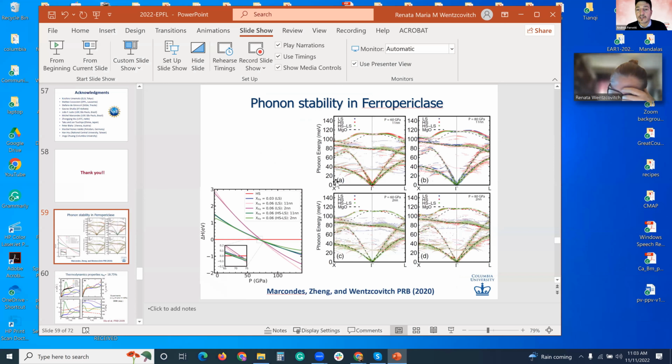That of course we can do within our simulations. So what is the reliability of our Quantum ESPRESSO simulations at these ranges? Can you comment on that? I think probably this comes back to pseudopotentials. Yes. Well, up to 135 GPa, iron with 8 electrons is pretty good. You don't need iron with 16 electrons. You need that above 150 GPa. You need iron with 16 electrons if you want it to be accurate.